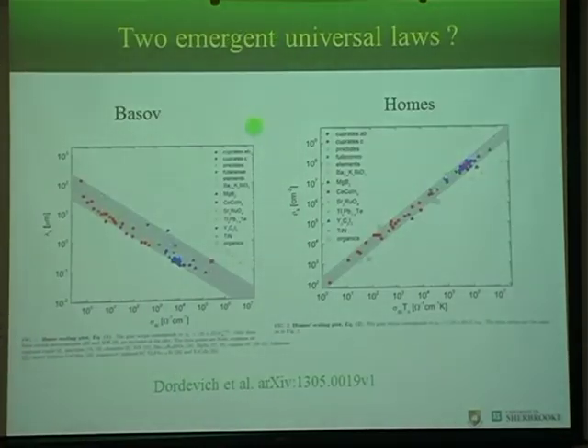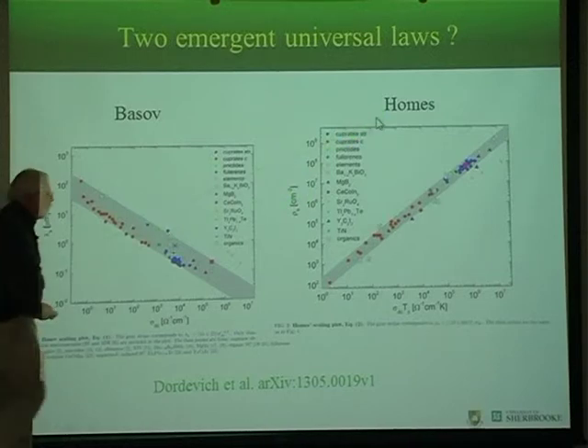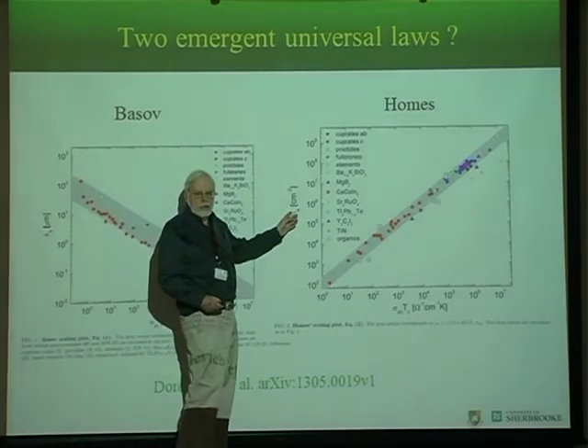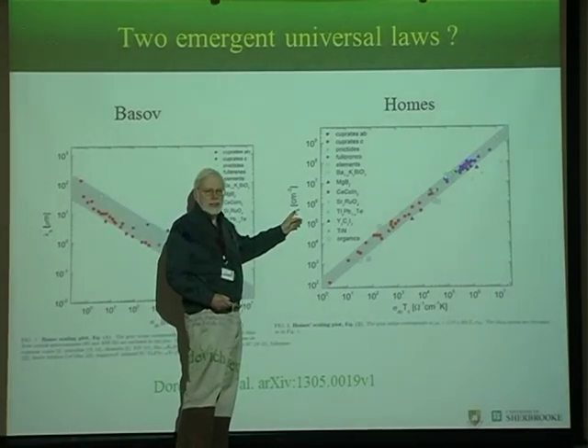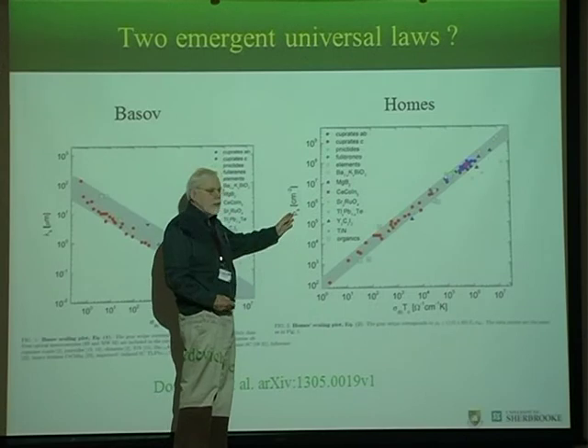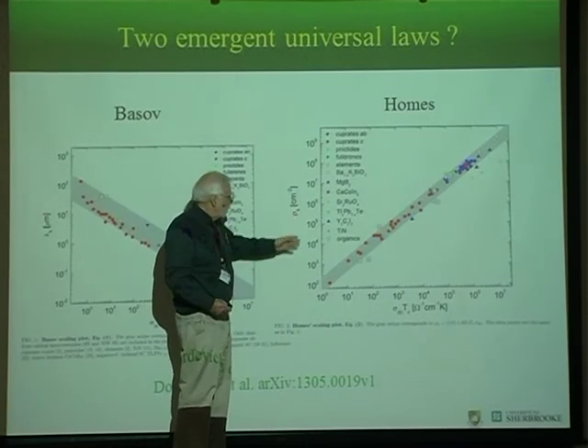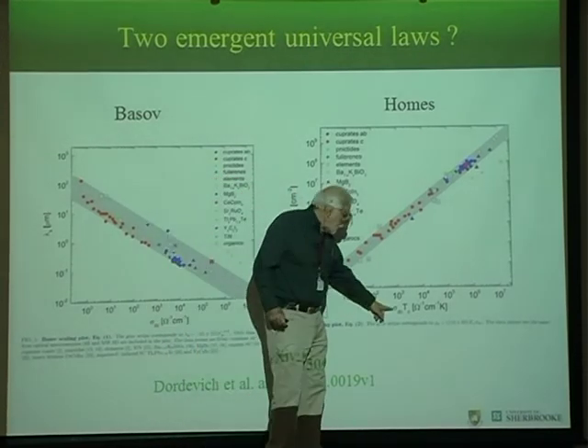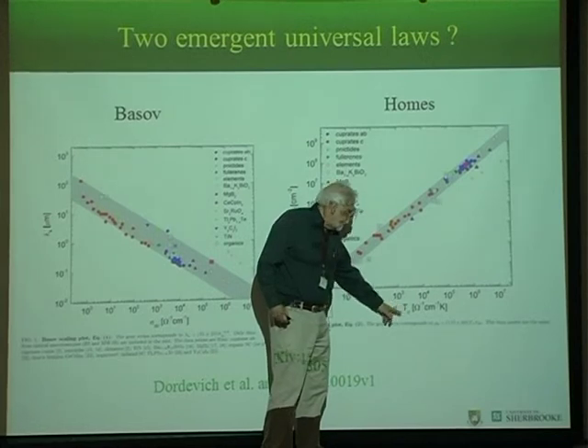Okay, so there are two laws that were proposed, and I don't know if they are emergent properties or not. And that's still a mystery in some ways. I'm supposed to tell you what is the mystery. So one of them is Homes' law, not the usual Ohm's law, but another one. So if you look at the superfluid stiffness, this is related to the penetration depth as a function of the DC conductivity times Tc.